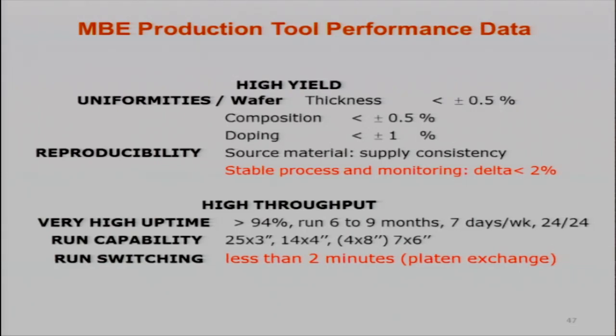Now, this MBE production system is very uniform. The uniformity of the thickness is 0.5% across the wafer. And then very stable. The most important thing I want to show you is the very high uptime, 94% uptime. You can have 6 to 9 months of running before you open the MBE system. It runs 7 days a week, 24 hours a day. That continuous running, you can run 6 to 9 months without opening the system.